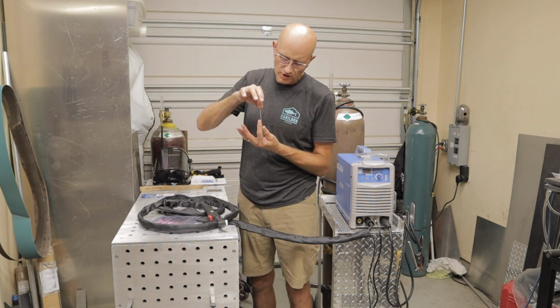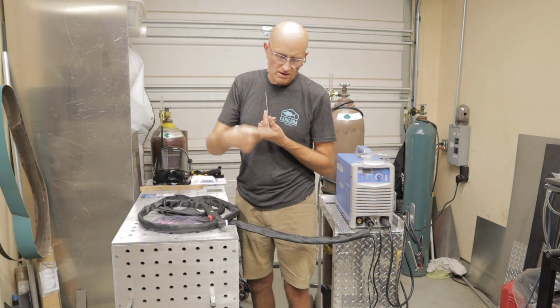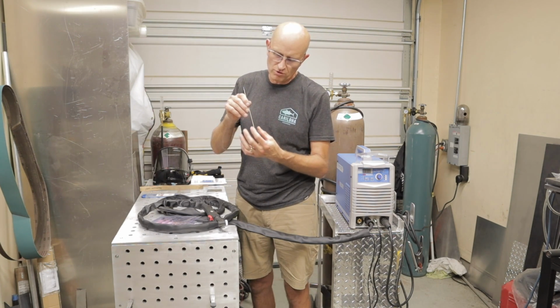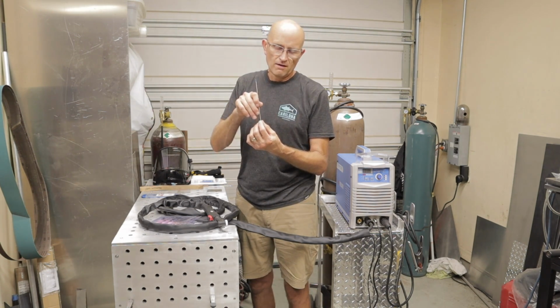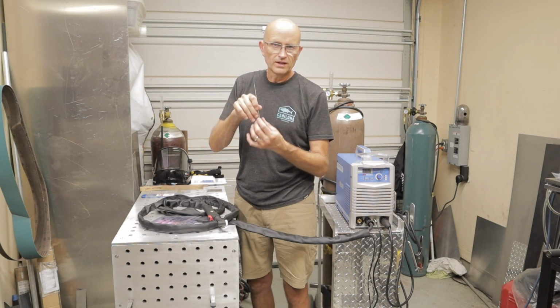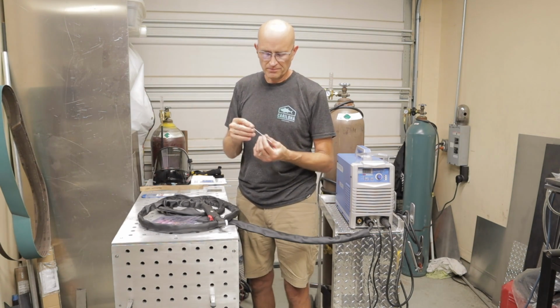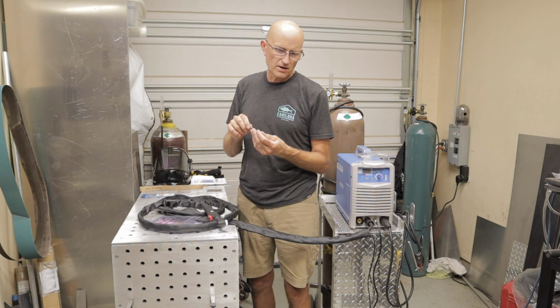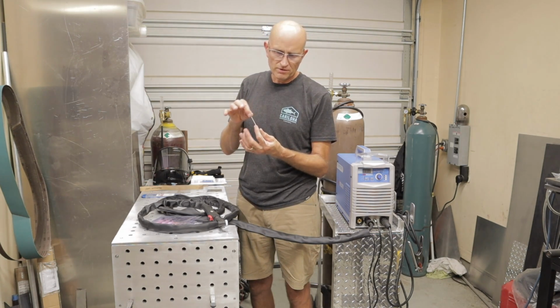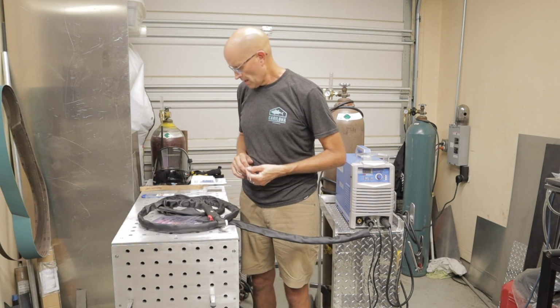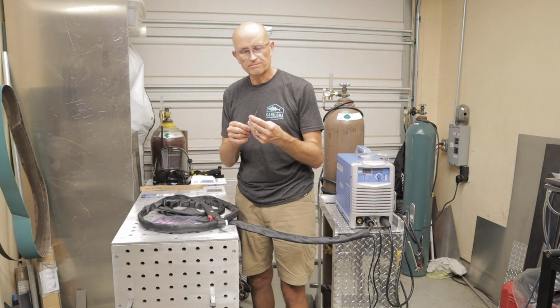And you basically want to hold it upright and let the grinder go downward, because you want your grinding scratches to go in line with the tungsten. I usually grind at about a 25 to 30 degree angle for most of my TIG welding. And that's what I've done with this one.